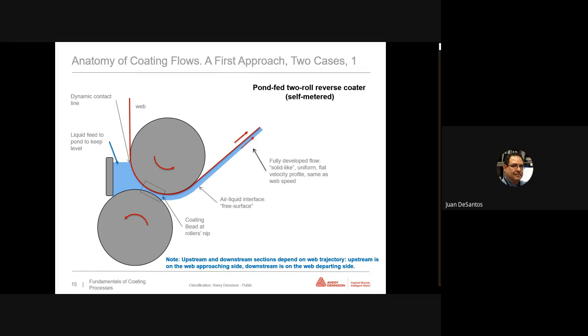So we can distinguish a region where most of the action happens, the strong part, where the metering of the final coating will happen. And this is called the coating bead. Here, the flow is almost parallel, but there are strong gradients in the direction perpendicular to the flow path. Now, there is also action here in the pond, but the velocities there are relatively weak as compared to the strong gradients that happen in the coating bead. In the place where the web plunges into the pond and is first wet by the liquid, we find what we call a dynamic contact line. It's a place where we force the wetting upon the web.